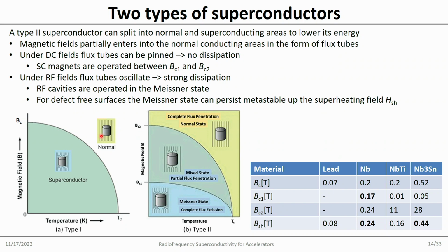However, a type 2 superconductor has what we call a negative surface energy. So what it can do is create very small normal conducting parts, where in these normal conducting parts it would allow flux to enter. Yeah? So basically it does not expel all the magnetic field, it lets some in while remaining the majority of the material in a superconducting state. This is what a type 2 superconductor does.